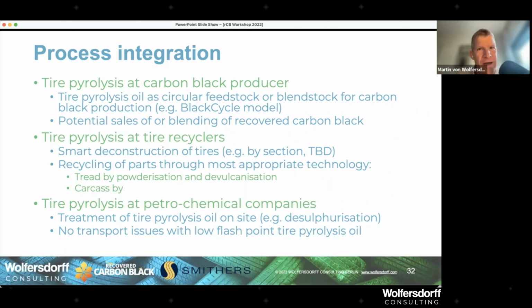But one idea of a smart deconstruction might be we really separate the different sections of the tire, which are glued together by the vulcanization. So it's not going to be easy, but this is the smart deconstruction, because then if we have the sections pure, within one section, we have a very defined chemical composition. And then we can say, okay, this is a nice material. This is the tread of the tire. It goes into devulcanization, and everything, the carcass, can go in the soup for the pyrolysis, and we recover out of the pyrolysis what we can.